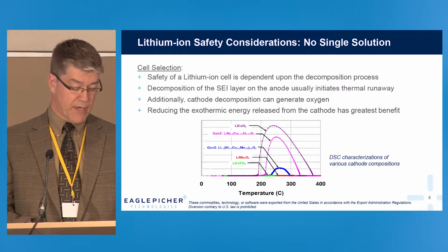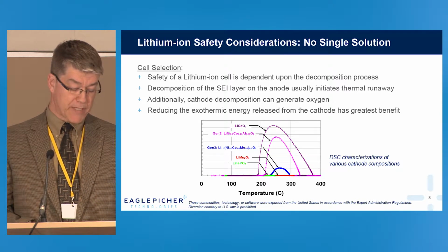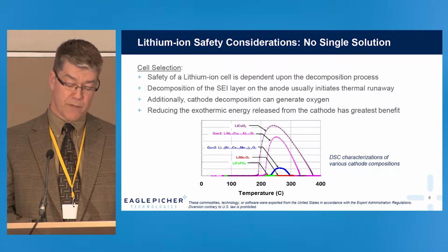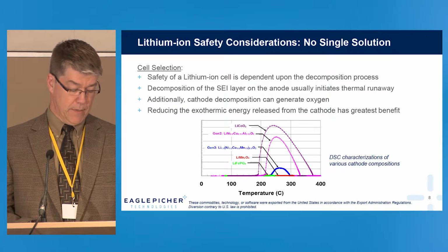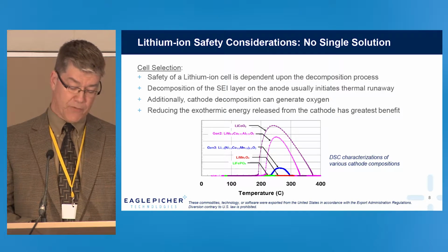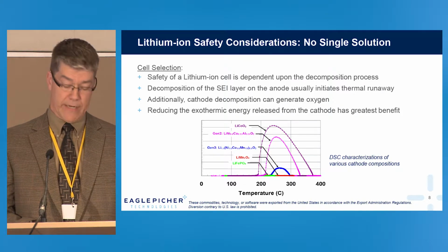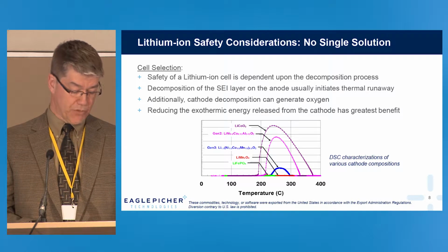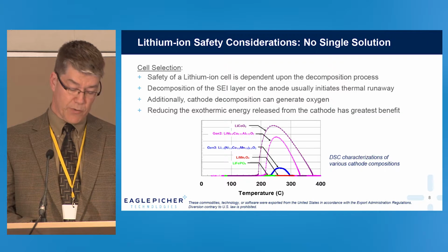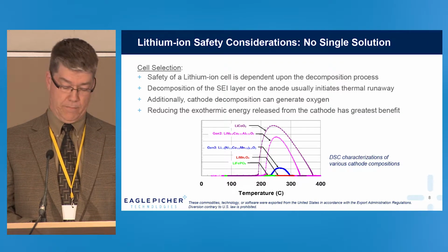When we look at cell selection, decomposition of the anode's passivation solid electrolyte interface can lead to thermal runaway. Cathode decomposition, as we discussed earlier, can itself generate oxygen to lead and feed combustion. So ideally, we'd seek to choose a less reactive electrochemistry to minimize the failure event.